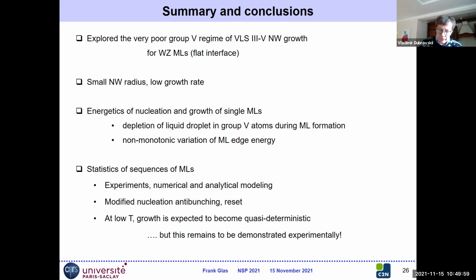And if we additionally consider the edge energy which becomes non-monotonic due to the boundaries, then we can even have growth at negative supersaturation. So basically, what you are saying is that we only need positive supersaturation for nucleation, but we can then grow at 0 or even negative supersaturation, which is amazing, of course. Do I understand correctly? That's what they are saying. Yes, yes, that's the outcome of this theory.